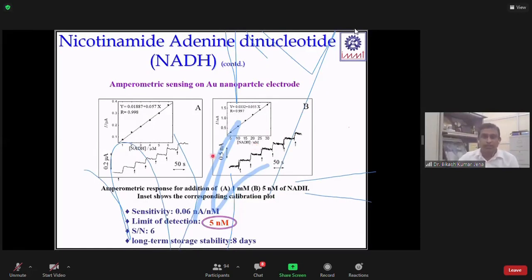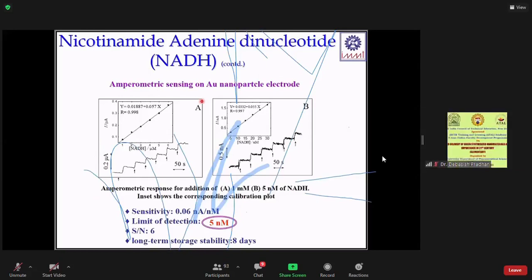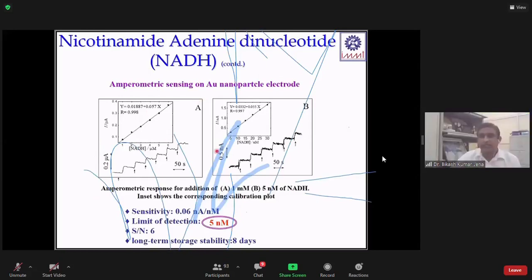So before that, we tried amperometric sensing with this gold nanoparticle-modified electrode, because amperometric sensing is quite a sensitive technique, as we are able to detect in the nanoampere current range. When we use this nanoparticle-modified electrode for amperometric sensing of NADH, we can see a very low detection limit, like low nanomolar concentrations of NADH can be detected. If enzyme activity generates such a low concentration of NADH, then this sensor can capture it.